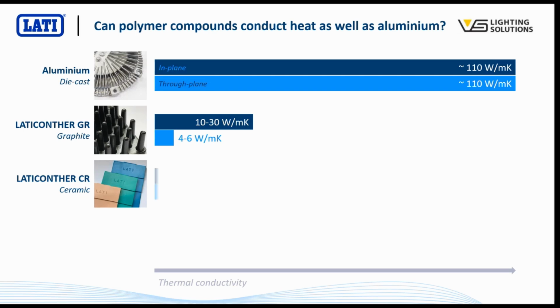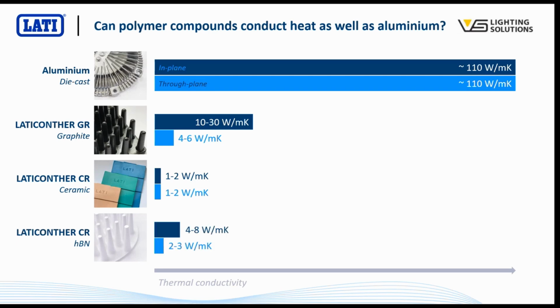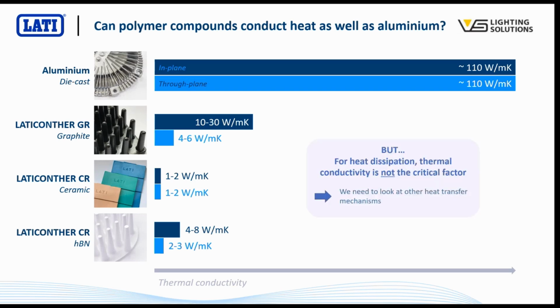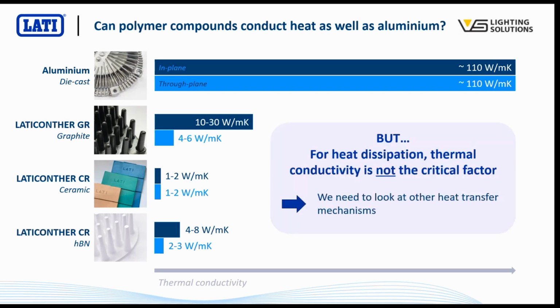And things don't look a lot better when we look at the ceramic-filled material. With the ceramics, the additives are more uniform in direction, so we don't get that same directionality, but the thermal conductivity is lower again. We have some other highly specialist ceramics that have a little bit better performance, but still not as good as the graphite-filled materials. So on the face of it, it doesn't look so good for the conductive plastics. But the key point to remember here is that for heat dissipation applications, thermal conductivity is not the critical factor. It's not the critical parameter that we need to look at.